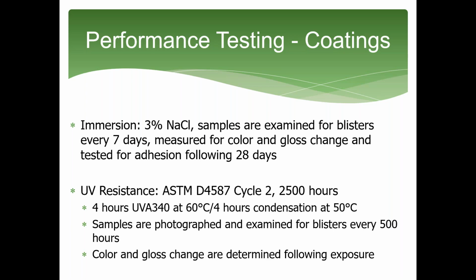UV resistance is performed using ASTM D4587 cycle 2, which is 4 hours of UVA light from UVA 340 bulbs at 60 degrees C, followed by 4 hours of condensing humidity at 50 degrees C. The total exposure time is 2,500 hours. Samples are examined for blisters, and they are photographed every 500 hours. Color and gloss change are measured following the exposure.